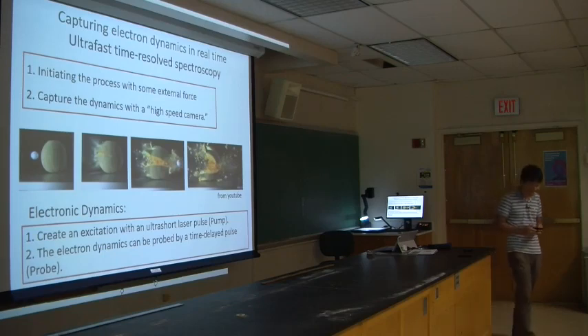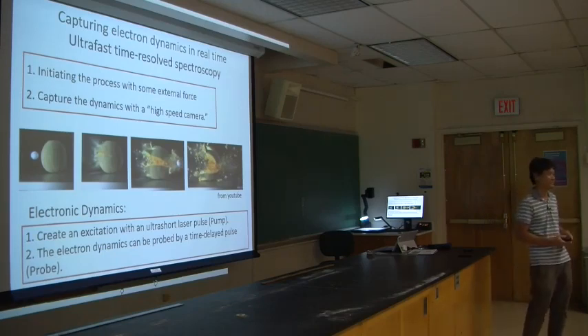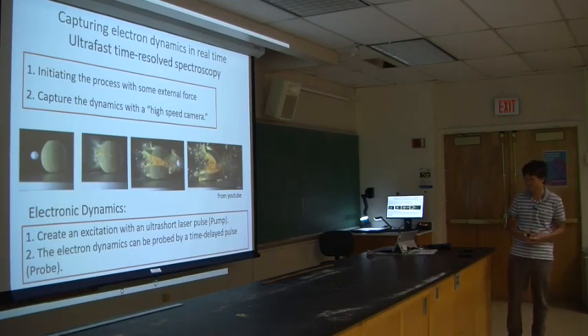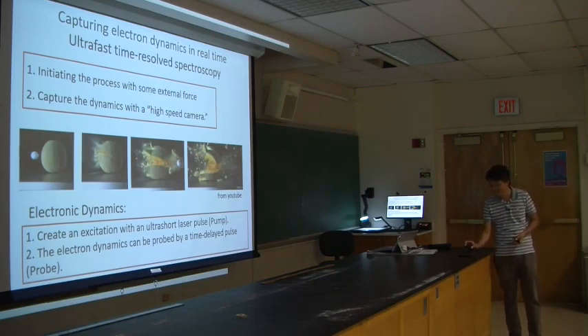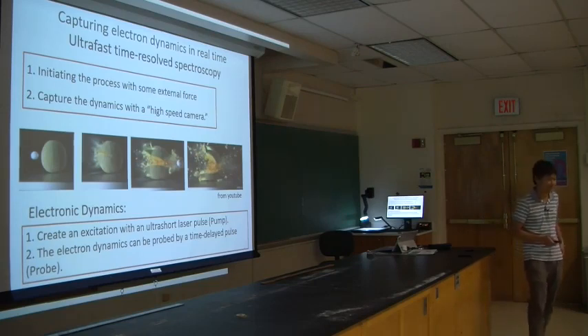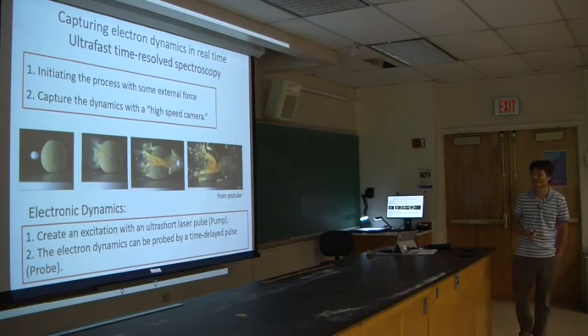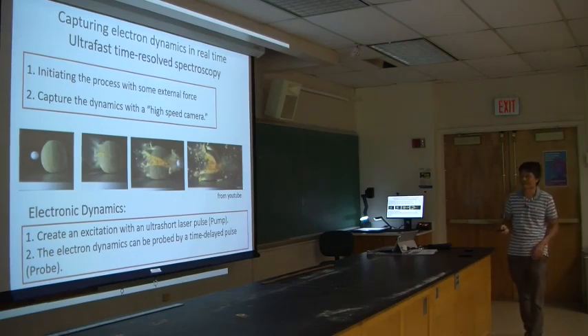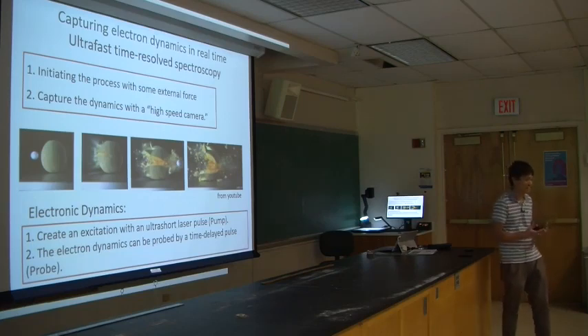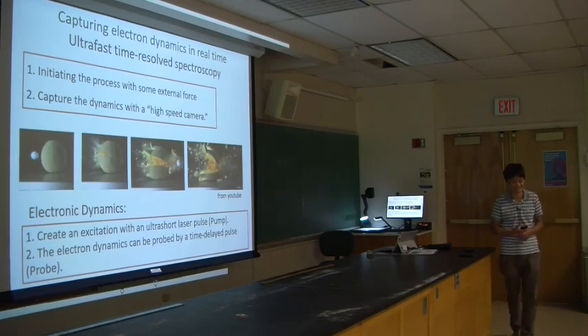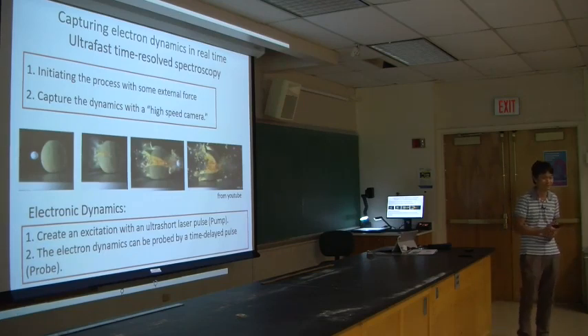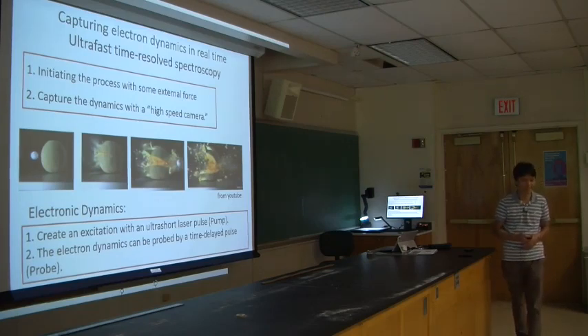So how do we tackle this problem? In my group, we use so-called ultrafast spectroscopy, right? Basically we try to capture the electronic motion in real time, just like a fast speed camera, but working at much higher time resolution. Typically, if we want to study this electron motion, we need something like 10 to the minus 15 to 10 to the minus 9 seconds, right? This femtosecond to nanosecond time scale.